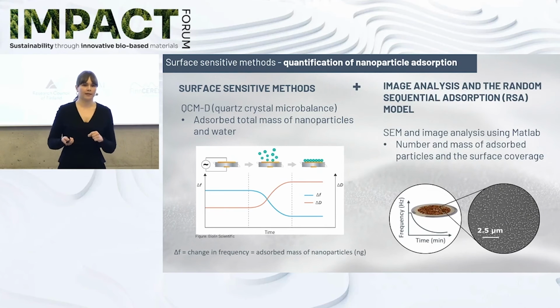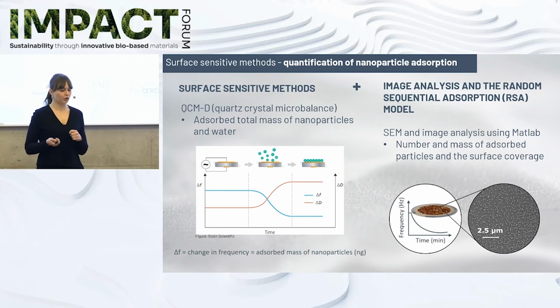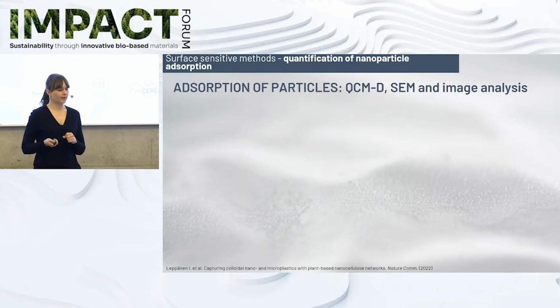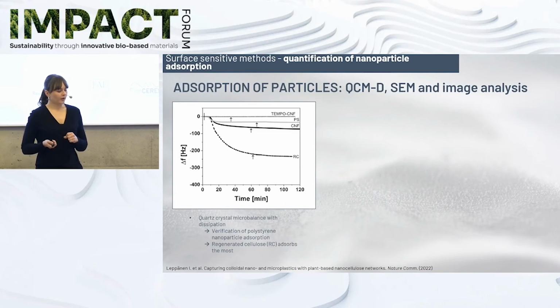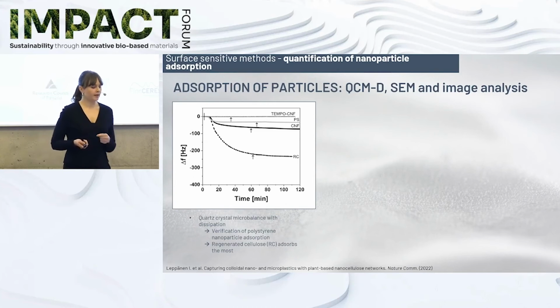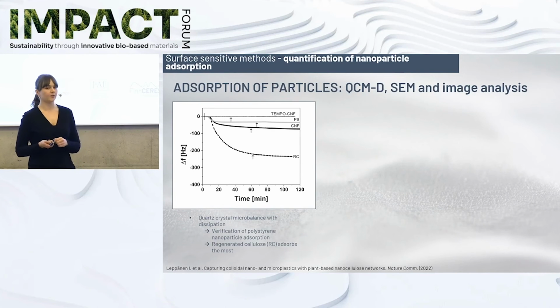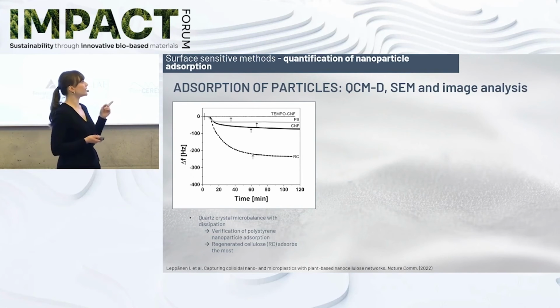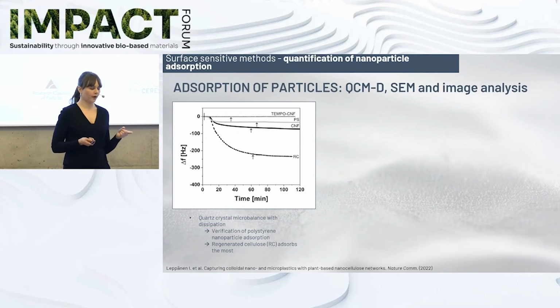And we have then combined this together with image analysis and modeling tools to kind of calculate the number of the adsorbed particles on these cellulose surfaces. So here you can see the QCMD results, and we see that there is this negative change in frequency, which indicated the adsorption of the particles, and we see that RC, which is regenerated cellulose, adsorbs the most of the particles. So it's very efficient in capturing the nanoplastics from the water.